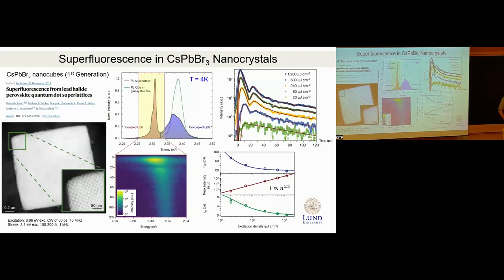So now, going to perovskites, in 2018, the Kovalenko group published this remarkable paper in Nature, where in well-ordered lattices of cesium lead bromide of the first generation, so if you remember the slide with the long synthesis I showed, these were size-selected particles from the first generation. What they saw was two features in the optical spectra at low temperature, a narrow intense feature attributed to superfluorescence. They saw oscillations as a function of time and excitation density, plotted signal intensity versus excitation density, and saw that it's proportional to n to the 1.5, not quite 2, but still superlinear. And then they saw shortening of the delay time, the time between this peak and 0, as a function of excitation fluence, which also fit together into this phenomenon.